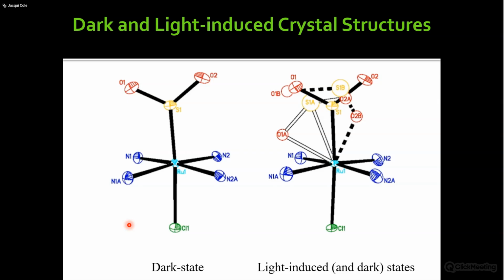And I've already hinted at this before, but this is the dark state, so that's quite easy to refine a structure. And the moment you see the light-induced state, because often you don't get full conversion of the sulfur dioxide, then you still see some of this dark state. And then you model it like a disorder problem. On top of the dark state, you model the light-induced species, right, which are really quite close.